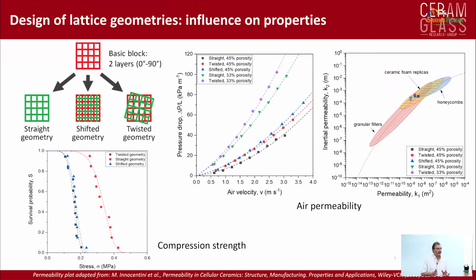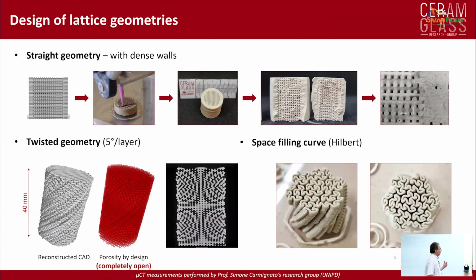We are interested in lattice structures, and I already demonstrated with pre-ceramic polymers, if you remember, that by modifying the assemblage of the layers, you can modify the mechanical strength and the permeability of the components. So we demonstrated that. We confirmed that also with geopolymers, and the results followed the same trend as already demonstrated.